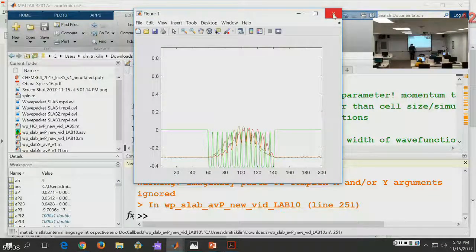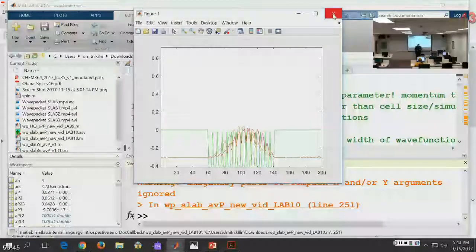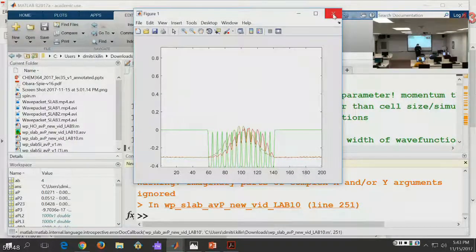Or if we do not want to bother ourselves with silicon and speak about charge transfer at the interface for very general photovoltaic technology, then we may speak of semiconductors that have different ionization energy. So you can take half of the layers with a little bit less ionization energy, another half a little higher. Then our goal would be to observe how the electronic density prefers to concentrate on one side over another. So this is something practical that we can explore and see on the yield of this reaction of electron transfer.